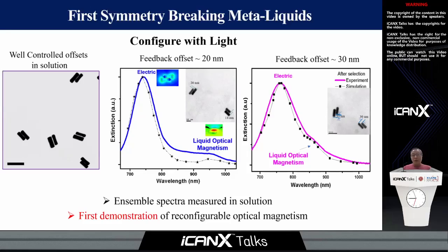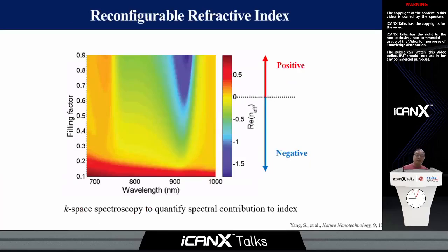With such uniform control, we observe a very distinct collective spectral response in solution that has well-defined electric and optical magnetism in our metamaterial. Essentially, this is the first demonstration of reconfigurable optical magnetism directly in solution and collectively. With such uniform control of the metamaterial structure, we can also reconfigure the refractive index by light. We use k-space spectroscopy to further quantify the electric and magnetic mode contributions of the metamaterials. And from this contribution, we can tailor the refractive index from positive to negative.